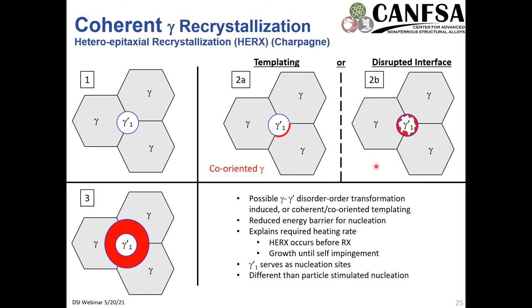Alternatively, what we've also observed is a disrupted interface at the primary gamma prime, and this could occur during the dissolution of the primary gamma prime as we are in this temperature regime, and the stability of that gamma forming there would be of interest. And in either of these cases, though neither are mutually exclusive of the other, they are both definitely possible, it appears. This would result in the gamma nuclei that formed, co-oriented with the primary gamma prime, growing to consume neighboring gamma grains of stored energy.